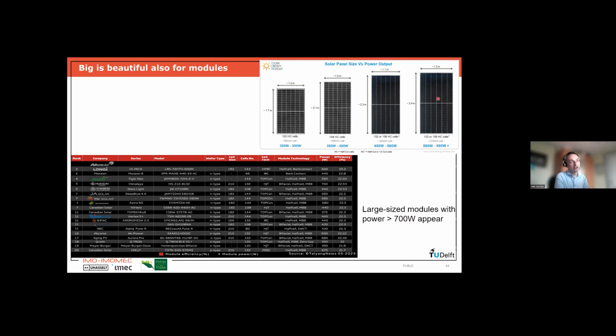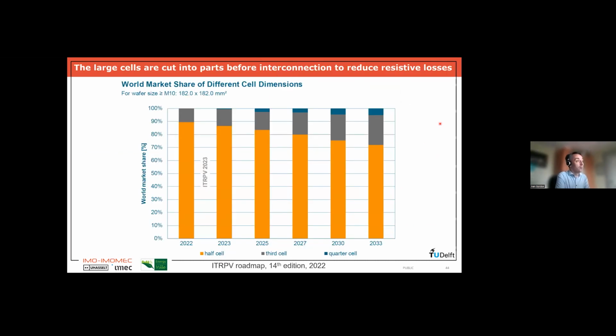But of course, these very large modules become very heavy. So probably we cannot make the modules much larger than this anymore, because then they become too heavy and it becomes very difficult to handle, etc. One thing that I should also mention is that because we now use very large wafers, such a large wafer is generating a very large current. And this is not so good because the current that is generated by the cell needs to be transported to the outside world. And if you have a very large current, you might have a lot of resistive losses.